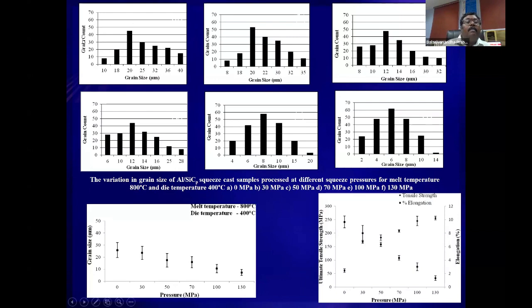Whereas in the case of conventional casting, it ranges from 10 micron to 40 micron, in the case of squeeze casting, sometimes you can see ranges from 2 micron to 14 micron. And also a greater improvement in strength is possible. Ultimate strength from some 70 MPa reaches 250 MPa. Also, another important thing is that the ductility will reduce. That's another challenge. But the mechanical property, especially the tensile strength, keeps on increasing with this processing condition. So if you couple squeeze casting with stir casting, you can get good mechanical property and also good microstructure.